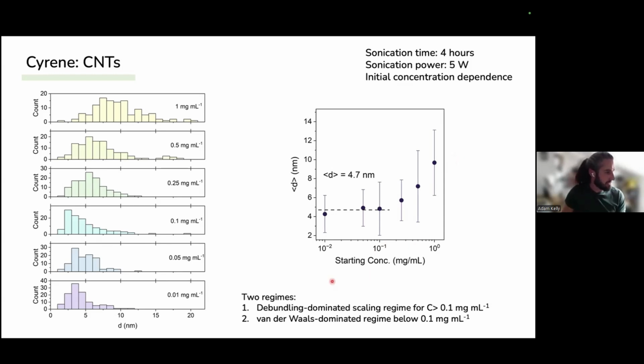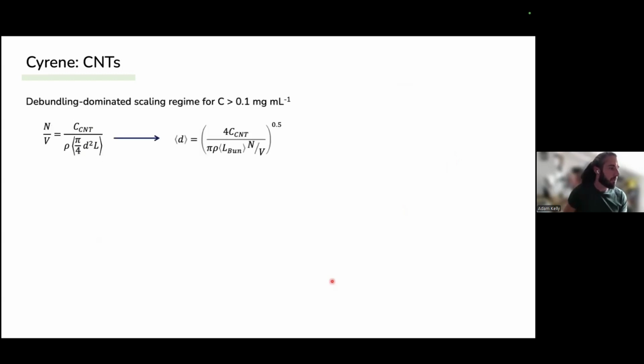And then we have a van der Waals dominated regime below 0.1 mg per mL. So what do I mean by these two regimes? Well, the debundling dominated scaling regime is where there is a lot of material in the dispersion. There's contact between the bundles, and the mechanical energy from the tip is transferred bundle to bundle to bundle, which allows them to debundle this way.